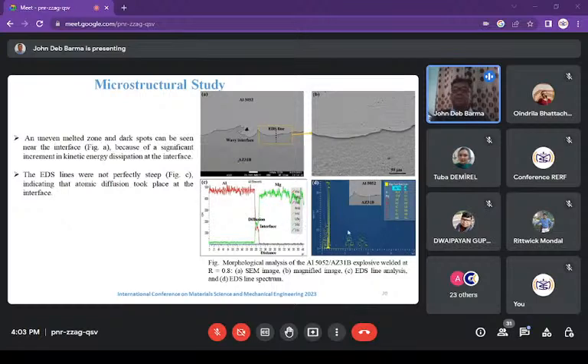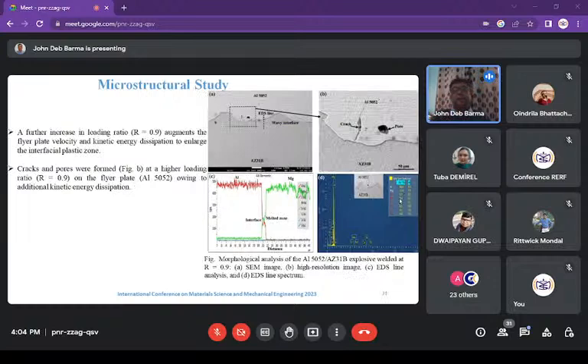And the EDS line spectrum, this figure, figure D, it shows that the interface contains 61.6% of aluminium and 37.4% of magnesium, while other elements like zinc, manganese, copper, silicon, ferrous, and chromium are also present. Okay. And after going for a further increase in the loading ratio, that is at 0.9,